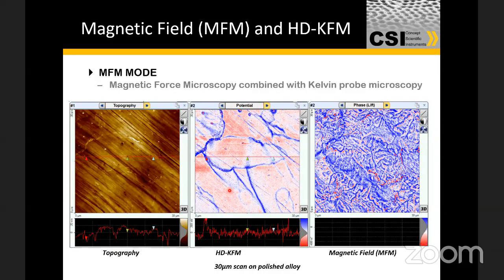Because this is a polished surface, the magnetic lift may be only down to about 10-15 nanometers. You only need to lift up by 10-15 nanometers, maybe, to be able to get the magnetic signal. So essentially it's just faster measurements, by being able to mathematically decouple multiple signals much faster than we were able to do 5 years back. That's really it.